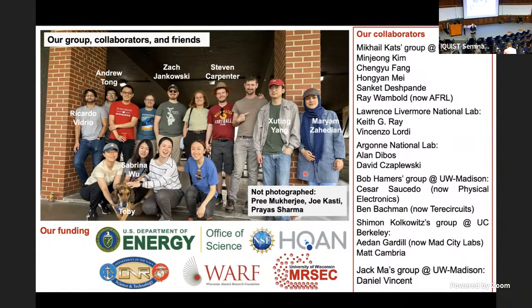Yeah, so that's the picture that we have based on our angle-resolved XPS data. And we find that basically for any oxygen-treated sample, sp2 is just pervasive. There's almost nothing we can do to completely get rid of it. If you start off with a hydrogen-terminated sample, I think that's probably a route towards starting with a very clean, well-ordered surface. And then after that, you can treat it with some kind of carboxylic acid, like Bob's group does, and that could help. We have limited success so far in doing that, because what we find is that we're not effective in removing all the CH bonds. So actually, we're interested in doing a spin study where we have partial coverage of the CH and then maybe a really low level of sp2 and overall slightly positive electron affinity, and see if the NVs are happy.